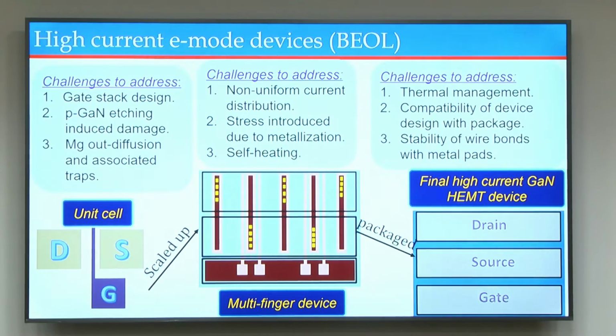What we are talking about is you need to ensure that there is uniform current distribution across the device. There is stress induced because of these metals, and we are talking about thick metals. We are talking about 5 to 7 micron aluminum and copper, and 1 micron vias all sitting on top of each other, right. We are talking about interlayer dielectric, which is more than 1 micron thick, because we are dealing with breakdown voltage in the range of 600-700 volts, right. So there should not be any vertical breakdown or breakdown because of the metal crossing. Self-heating effects are also something very important to be addressed here.